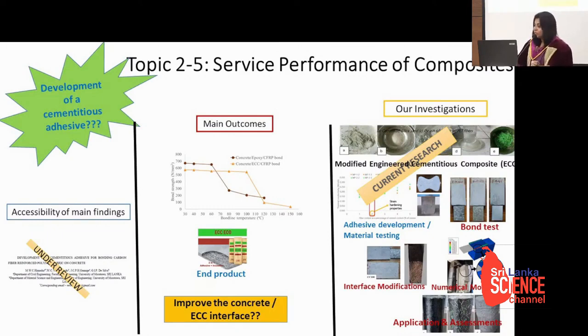So we thought, if that's the problem, we have to improve that interface. We made a number of attempts and finally we could improve the interface and achieve a more stable relationship under elevated temperature. So this is suitable even for a little less strength. It is suitable for outdoor structures. But we realized that the failure mode has shifted to the interface between concrete and ECC, the modified engineered cementitious adhesive. So that means if we can improve the concrete ECC interface, that means surface energy, we may be able to achieve higher strength than this.